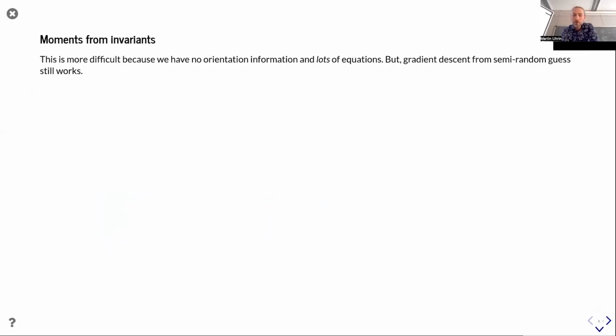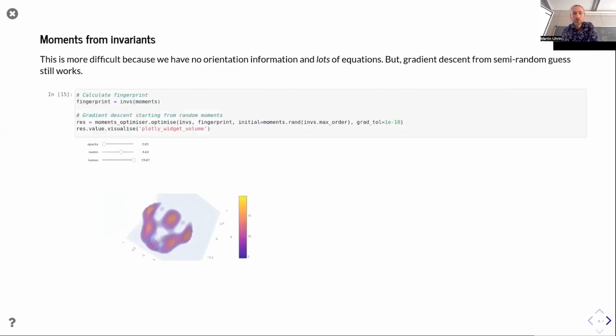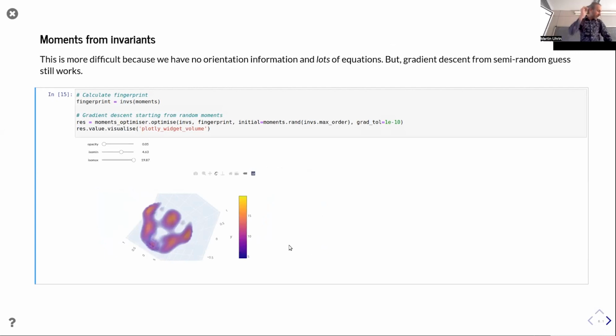But the step before that is actually a bit more difficult. So what do I mean by that? Going from the invariance, which you can think of as being similar to the intensities you get from an X-ray, right? So you know that once you get this diffraction pattern, you still need to do something to get the atoms back. And that's because in that case, you've lost the phase information. So you don't have everything you need to get the original atomic structure. Here I'm doing effectively the same thing, except in spherical harmonics rather than plane waves. And I invert this numerically.